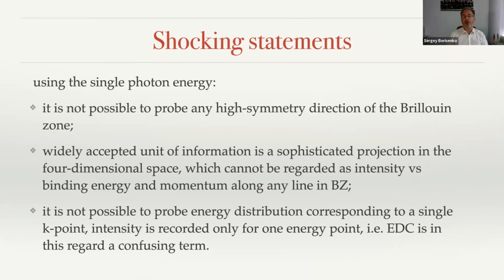And one can, of course, always add something, strictly speaking, but I will show you that indeed these statements are correct. In particular, it is not possible to probe any high symmetry direction of the Brillouin zone, for instance. This widely accepted unit of information that you always see on the screen, momentum versus binding energy, is actually a non-trivial data set, which is an excerpt from the four-dimensional space, and it cannot be regarded as intensity versus binding energy and momentum along any line in the Brillouin zone.